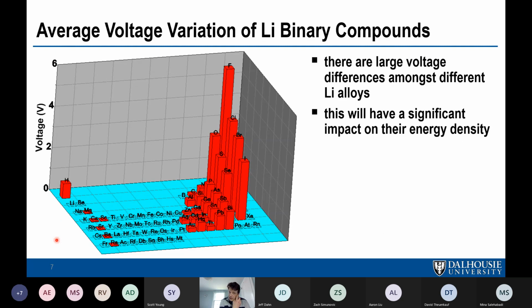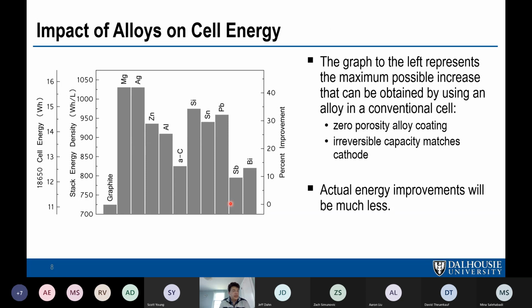And we could plot the potential of these materials that form alloys with lithium, and you can see there's quite a variation. So you would expect that this potential could have a big impact in the energy density of a cell. And indeed it does. So if instead of plotting volumetric or specific capacity of these materials, you plot the stack energy density in watt-hours per liter, then you can see a different pattern forming. Silicon is no longer the material that is the largest, I guess, in this graph. In the previous graphs of volumetric and gravimetric energy capacity, silicon had the highest. Here it doesn't, because its potential is higher than silver and magnesium. So according to this graph, if you wanted to choose an element to give you the highest energy density cell, you would choose magnesium or silver.